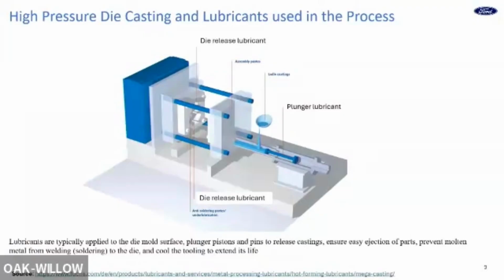potentially react with the die surface and cause some diffusion and make it difficult to release from the die. So lubricant is normally applied on the die surface, no matter the cover side or the ejector side, so it can form a protective film. But you can imagine that with contact with the liquid metal, the lubricant can be oxidized and leave some residue